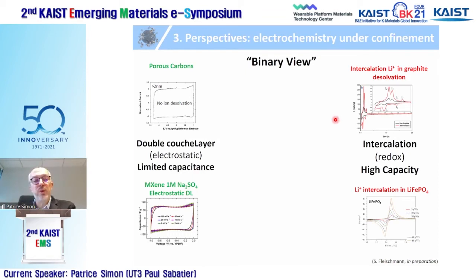On the other extreme end of the process, you have what we call lithium intercalation. This is, for instance, what happens in graphite negative electrodes in lithium-ion batteries, where you intercalate lithium ions, fully desolvated, between the graphite layers. By doing that, you have full charge transfer between the lithium and the carbon, and you have a redox process with high capacity. Here you also have, for positive electrodes, the same for the LFP electrode, LiFePO4: lithium ions are intercalated, fully desolvated, and you have full charge transfer, and you can recover the full capacity of LiFePO4. So still, this is high capacity during the intercalation reaction of desolvated lithium.